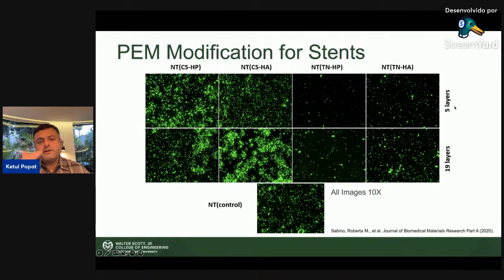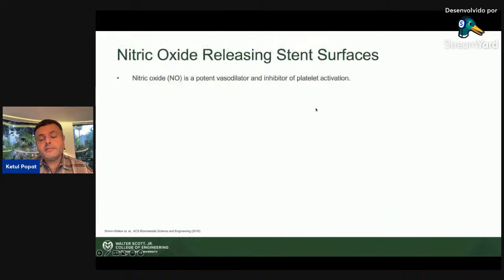Now, here we made different layers, 19 versus 5 layers, just to see what happens to these layers. It didn't make a lot of difference to have more layers because the smaller number of layers were much better. TN-HA was actually not as bad as these chitosan ones, but it was not great as well. So we thought that this TN-HP is something which is very, very interesting.